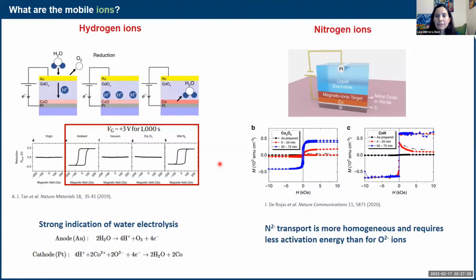So we can also see other types of ions, like nitrogen ions. Once again, this approach is more from the electrochemical side. Here they could see that they could grow cobalt oxide and then convert it back into cobalt, and that goes nicely between these two states, the ferromagnetic state, and then changes back to a paramagnetic state.